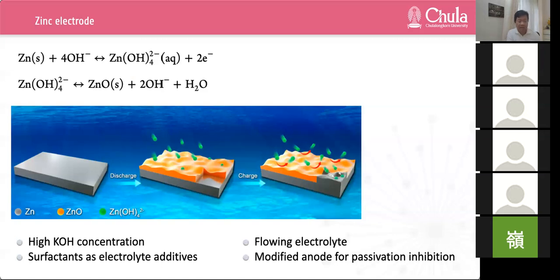And the insulating zinc oxide passivation film terminates the discharge process, reducing the utilization of the zinc electrode and the battery capacity. It also prevents the reverse conversion of metallic zinc, limiting the battery rechargeability. A small number of studies focus on the mechanism of passivation. At high current density, compact zinc oxide layer form to passivate the electrodes. At low current density, porous zinc oxide layers form, and passivation will not occur when the mass transfer of hydroxide ion across porous zinc oxide layer is enough for anodization.